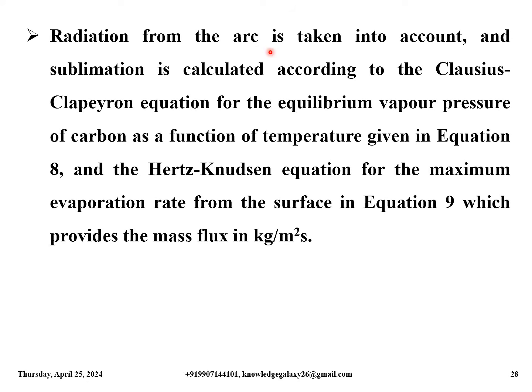Radiation from the arc is taken into account and sublimation is calculated according to the Clausius-Clapeyron equation for the equilibrium vapor pressure of carbon as a function of temperature given in equation 8 and the Hertz-Knudsen equation for the maximum evaporation rate from the surface in equation 9, which provides the mass flux in kg per square meter second. So these are the two equations which I have just mentioned, equation number 8 and equation number 9.